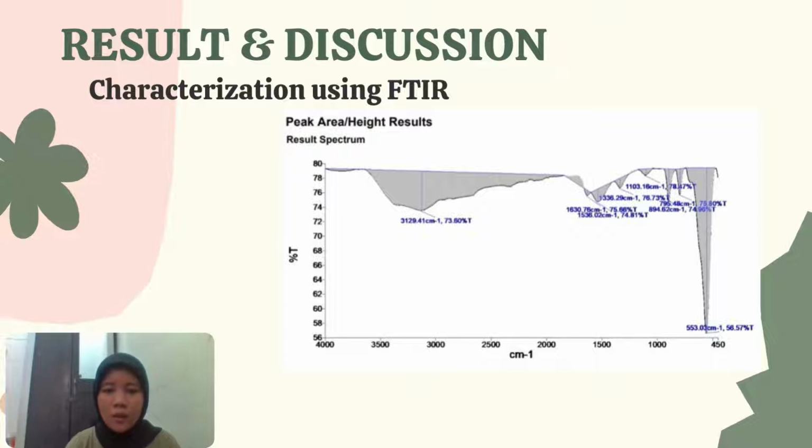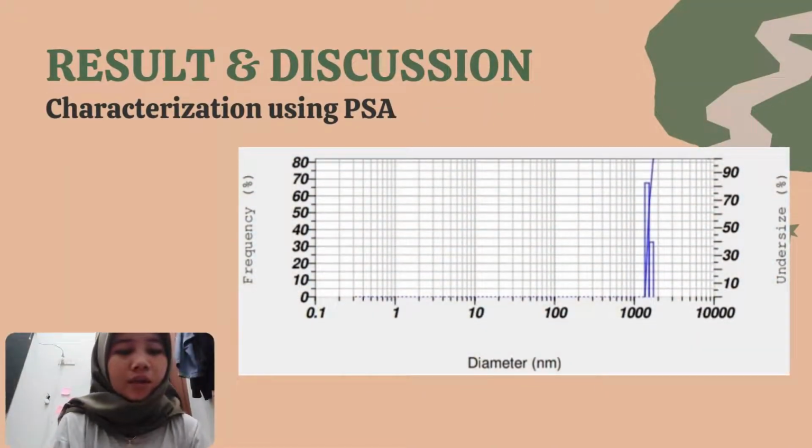The Fe-O vibration obtained is relevant to the reference magnetite wave number of 550 until 630 cm-1. The iron oxide nanoparticle powder resulting from precipitate was also characterized using a particle size analyzer,